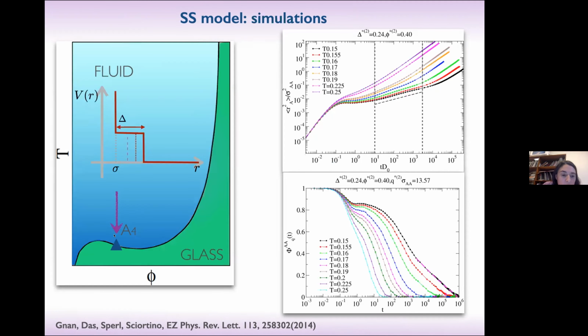Similarly, the second A4 was also confirmed. And in this case, these are the data for another delta and another packing fraction, now varying temperature. And we saw again the emergence of this subdiffusive behavior in the mean-square displacement and the logarithm here. These were very long simulations, and you may notice that these curves are kind of weird, because you first see the standard two-step relaxation also here, and then the logarithm comes much later, which is kind of intriguing.